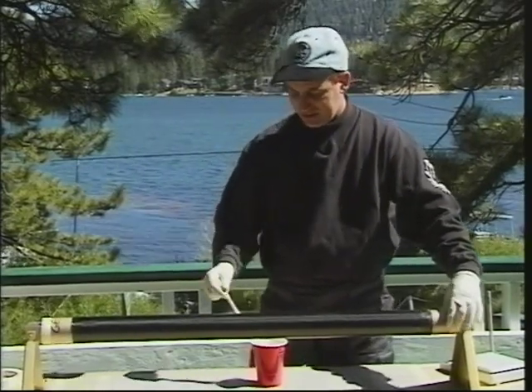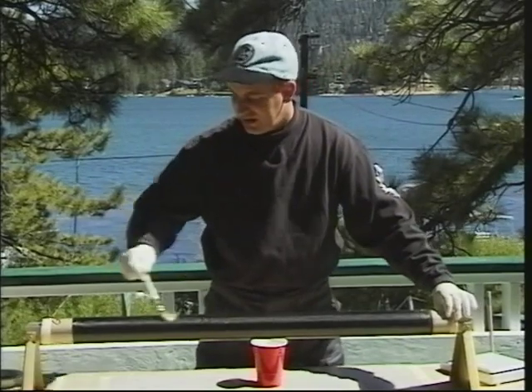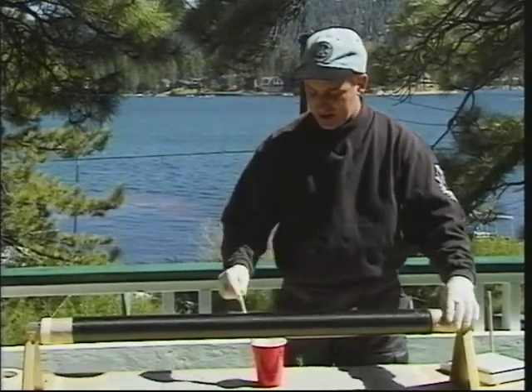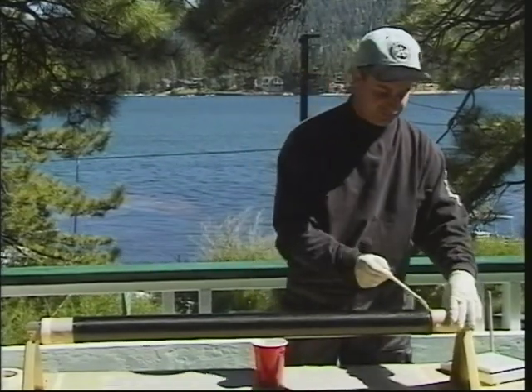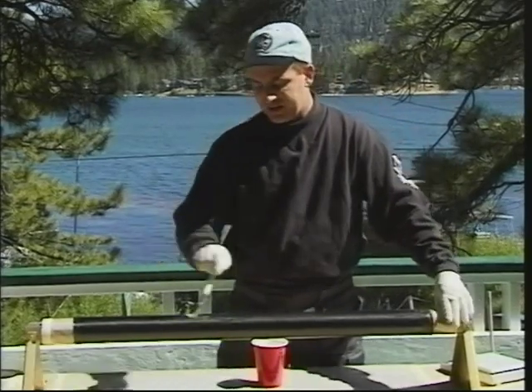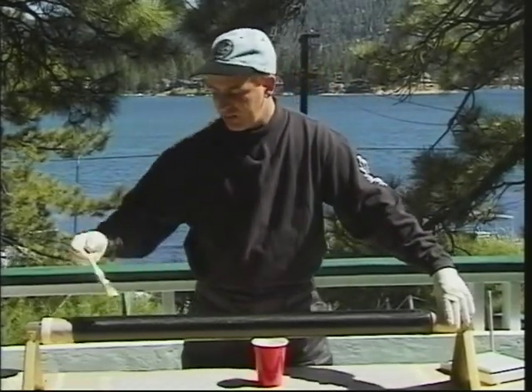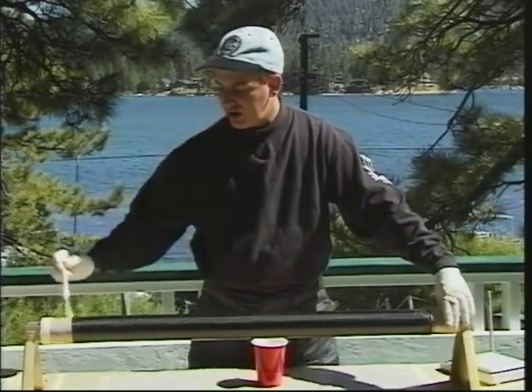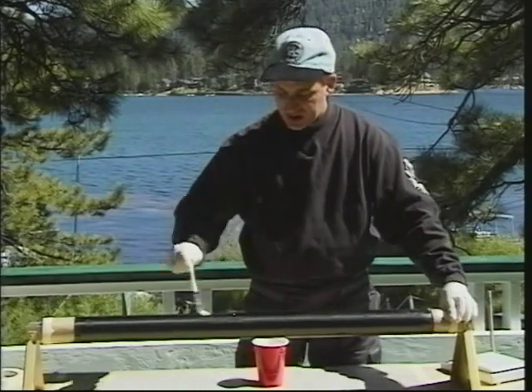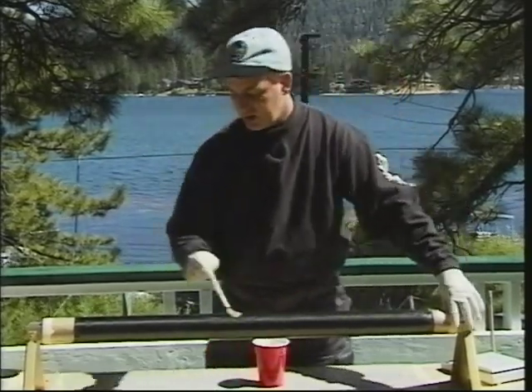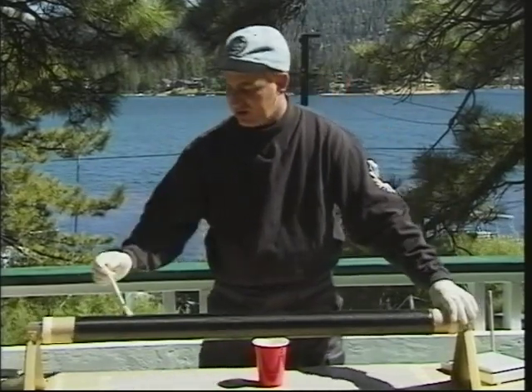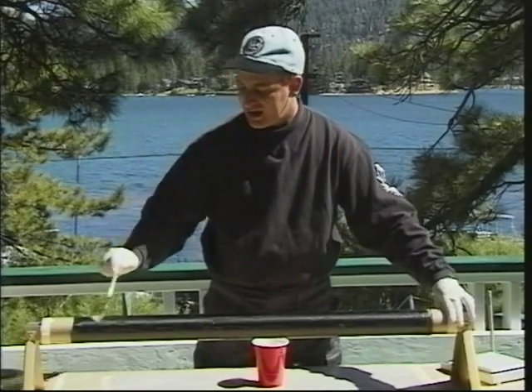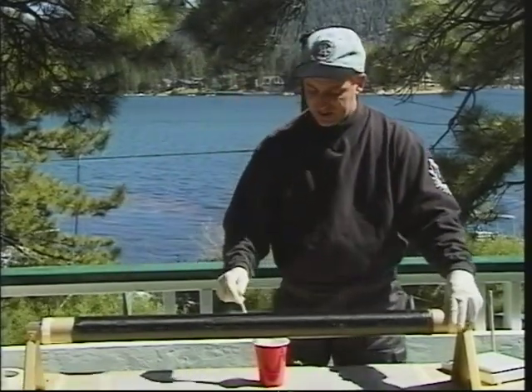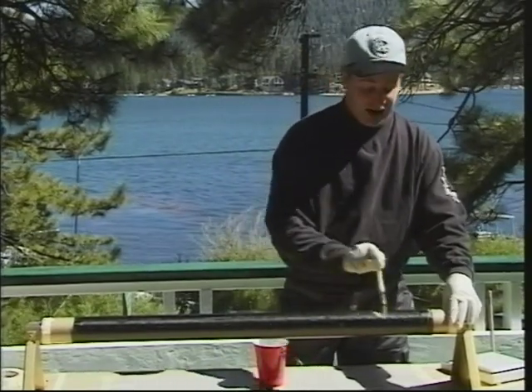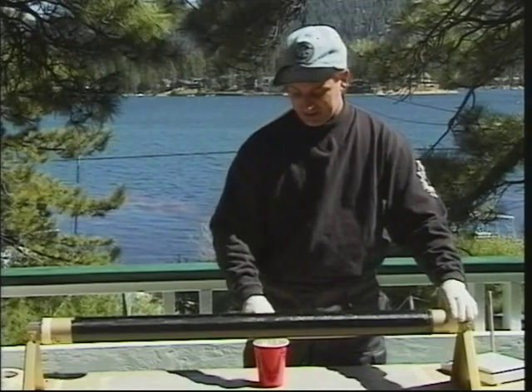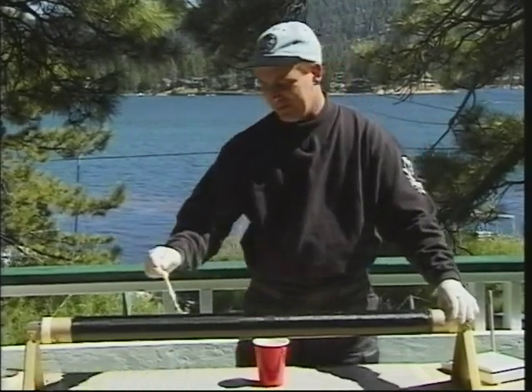Now I'm only doing this to get a little extra resin in there so that when we start our heat tape winding, it's going to really compress those layers together. I'm sure a lot of you have heard about the process of vacuum bagging. We'll be doing vacuum bagging demonstrations in another video. It's quite involved, and it takes a lot of time to go through all the idiosyncrasies of vacuum bagging. But this heat tape winding process that I'm going to show you is a way to get that same kind of vacuum bag quality out of the composite laminate without the vacuum bag and without the vacuum pump and the $150 extra of material that you'd have to get to do the vacuum bagging process. So